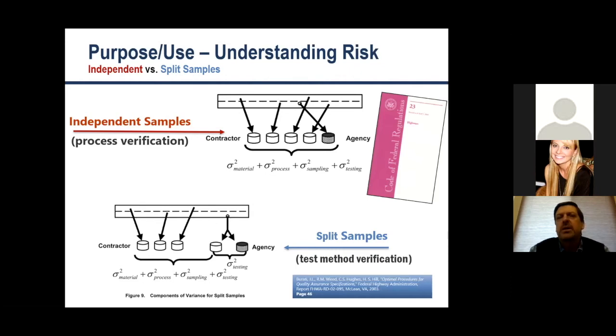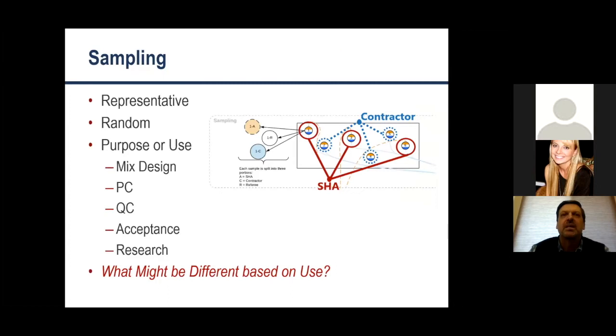split samples can be used depending on the situation, but as long as it's not for verification of quality assurance tests by the public agency, basically with PWL type specifications. It's really important to make sure we're getting the right kind of samples. I don't know how many times I went to pre-construction meetings and there'd be an agreement between the RE and the contractor to go ahead and have the contractor pull samples and split them for the agency and for the contractor, when they were really supposed to be pulled independently. So the other thing is, again, making sure we've got representative samples.